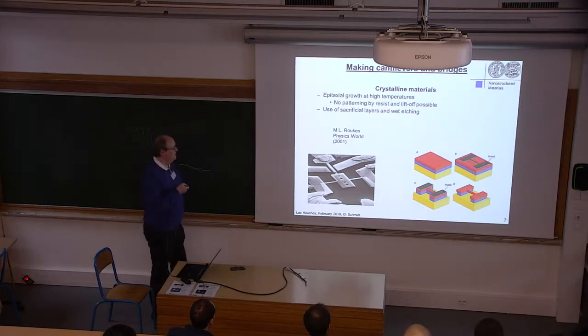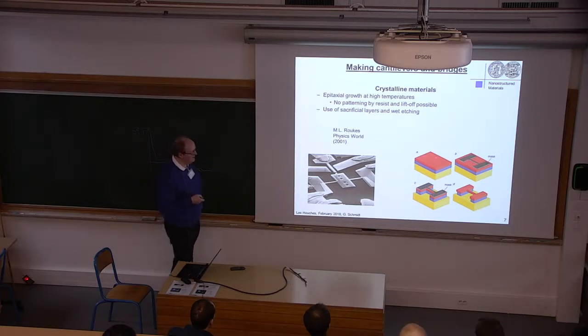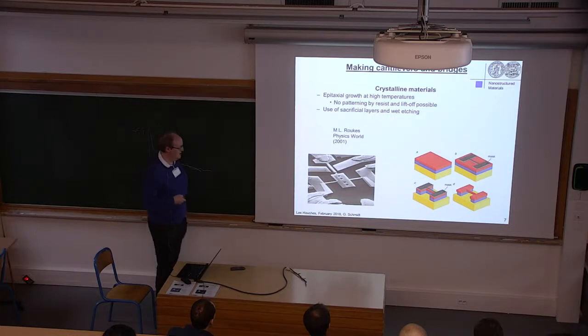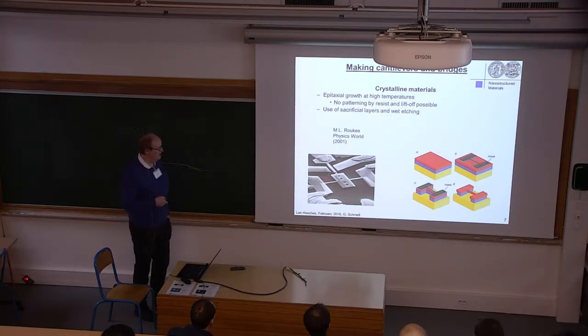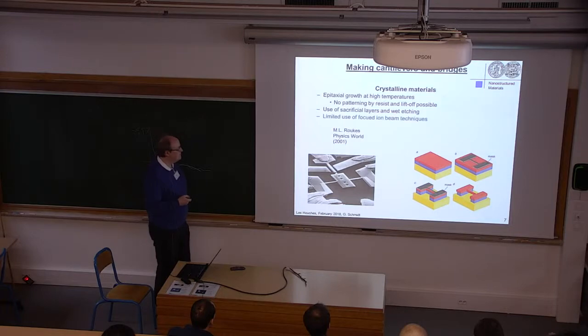So normally what you do is you use a sacrificial layer underneath. Here, for example, you see this is the sacrificial layer. The red layer is the one out of which you want to make your resonator. You put a mask on top, and then you do some dry etching going down here, and then you can remove the sacrificial layer underneath, and then you have your resonator. So this is standard stuff, and you can get devices like this, for example.